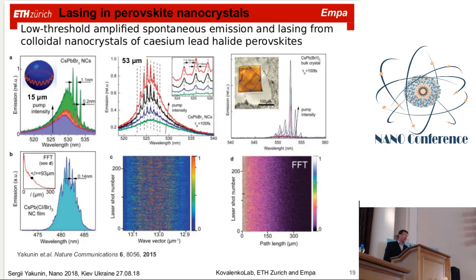Then of course we were interested in what about lasers? A very simple and easy way to make an optical resonator is to use just silica microspheres. So we took these microspheres and conformally covered them with a thin layer of perovskite nanocrystals, and after optical pumping we see a nice effect of whispering gallery modes, which look like equidistant lasing modes and show a certain threshold. And by playing with the size of the microsphere, we can also vary the distance between those modes. Again, we observed the whispering gallery mode effect in microcrystals of perovskite, and we also observed certain lasing effects in a thin film without any resonator.